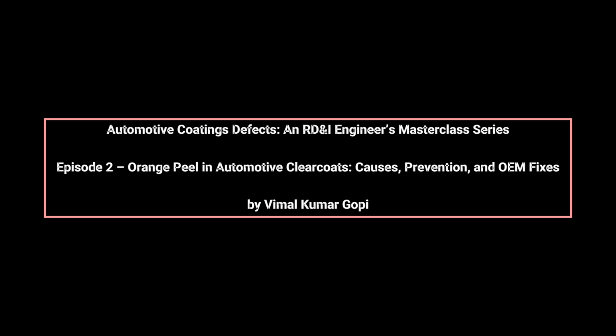Environmental conditions amplify or mitigate these formulation and process effects. Booth temperature, panel temperature, and relative humidity dictate the rate of solvent evaporation and, therefore, the window available for leveling. Warmer air or panels accelerate surface evaporation, reducing flow time, while cooler conditions increase viscosity, limiting wet film movement.